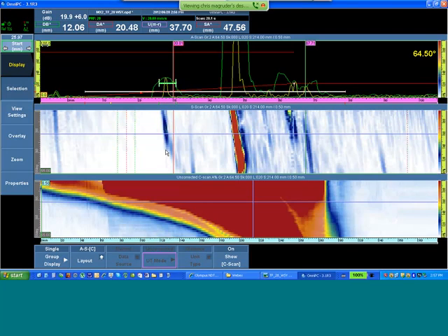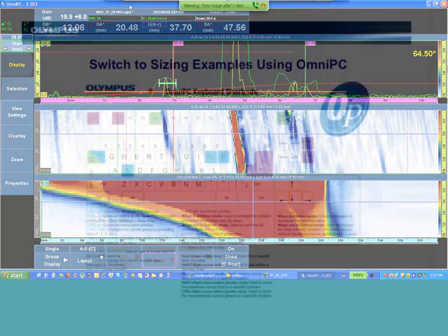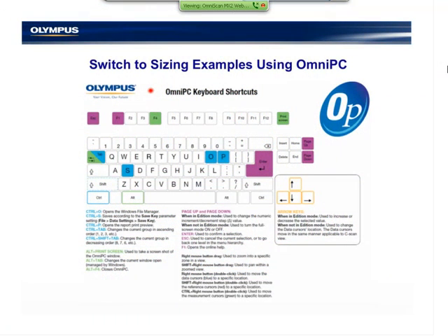A very typical high-angle L-wave ID creeping crack detection technique, often used in the power generation in-service detection, and we can see the benefit of the 70 to 55 degree sector scan. Using the same technique gives us very, very accurate sizing techniques. So we're going to wrap the webinar at this point.